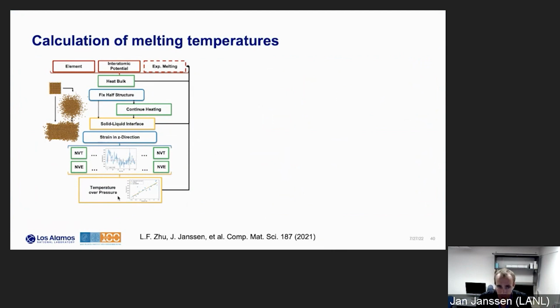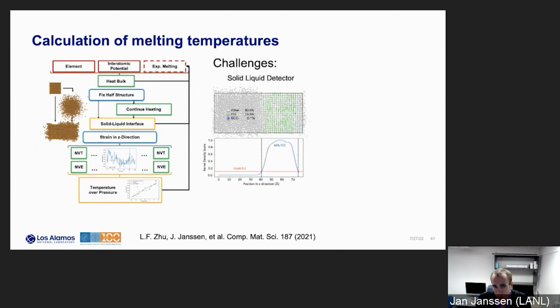Here I show the detection of a typical software, common neighbor analysis, and we see that the liquid phase is correctly identified as liquid. But within the solid region, where we see the atomistic columns here, some of these atoms cannot be clearly identified, right? So the software doesn't know if they're solid or liquid, and only 20% can be really identified as solid. But by combining this information with a kernel density score, we are really able to see that 46% are solid, and then the rest is correspondingly liquid.